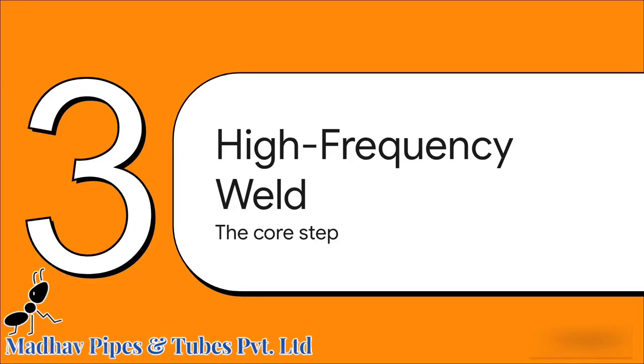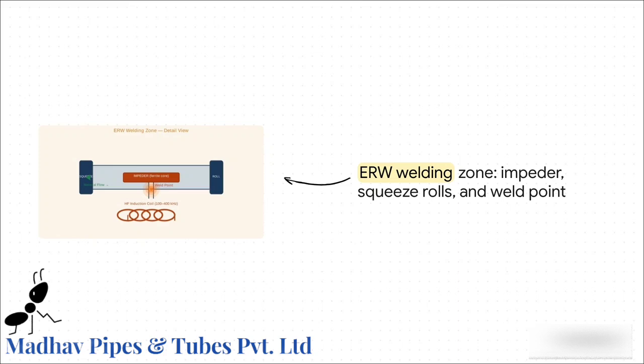Which brings us to Section 3, the high-frequency weld. This is the core step, and really the absolute climax of the manufacturing process. Now, what's genuinely fascinating is exactly what happens inside that weld zone. As the open tube edges pass through, they converge at a very precise V angle, usually just about 2 to 7 degrees. And positioned perfectly at the center is the impeder. This is a ferrite core rod sitting completely inside the tube. Its job is absolutely crucial. It acts almost like a magnet, precisely directing the electrical current so it travels exclusively along the very edges of that V-shape.